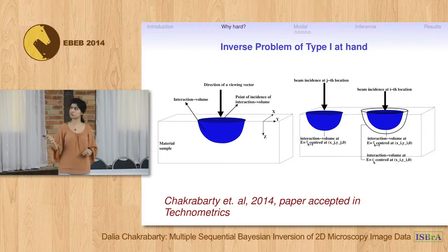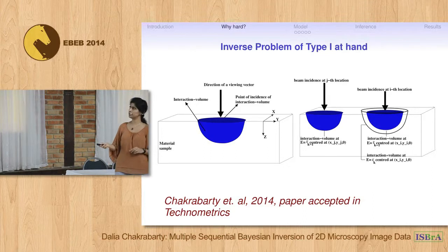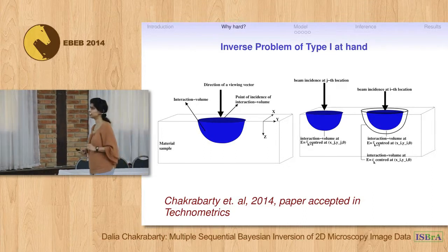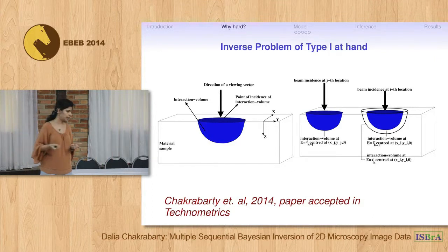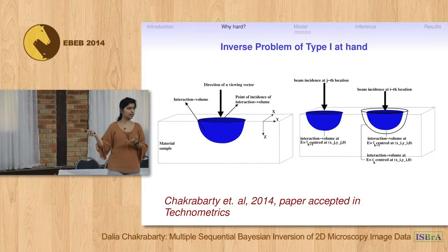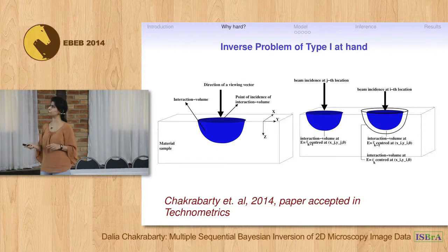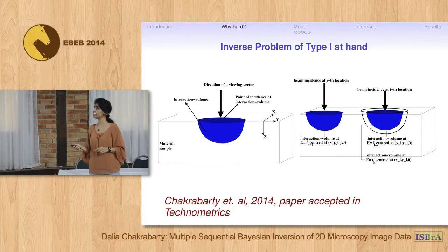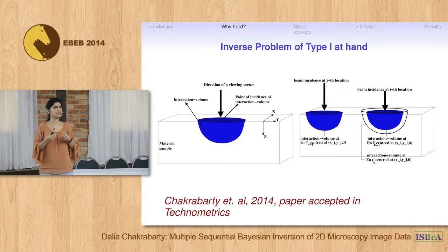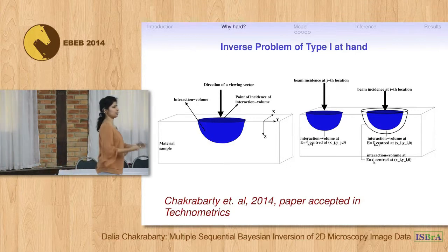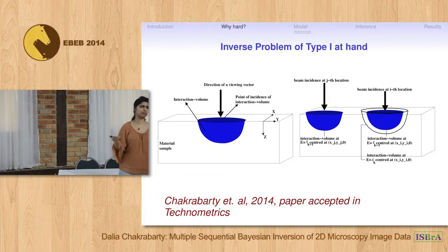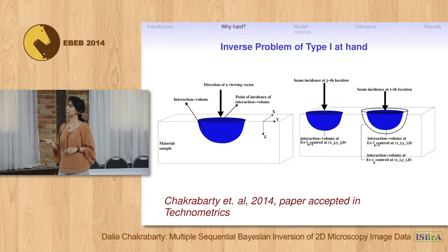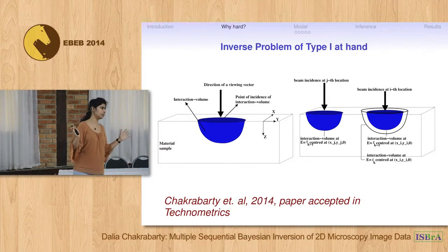As a result of these interactions, the electrons lose their energy and come to a stop after travelling some distance. This three-dimensional region inside the bulk defines the remit of the electrons — the region in which all atomistic interactions between the electrons and the material molecules occur. Microscopists refer to this as the interaction volume, shown here as the blue bowl-shaped region. Following microscopist theory, we model the shape of the interaction volume as a hemisphere centered at the beam location.